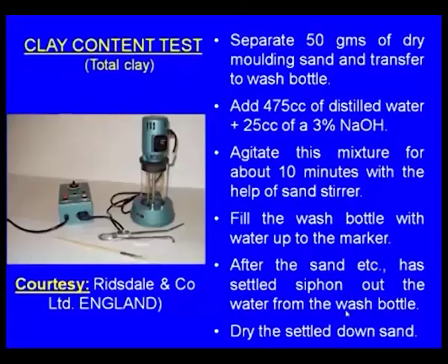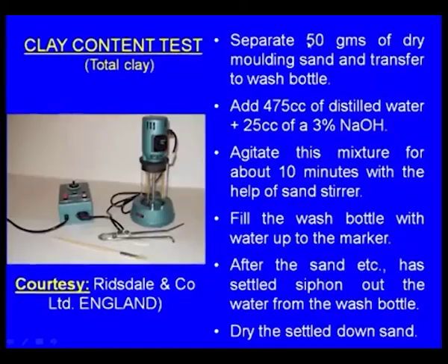Now while the clay is still mixed with the water, we siphon it out using a siphon. Now what is there inside the bottle? Only the fine, clean base sand is there. Clay has already been siphoned out. Now this sand is to be dried. Remember, in the beginning we have taken 50 grams of the sand.